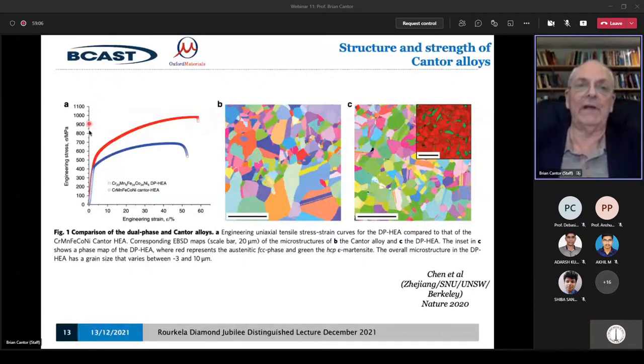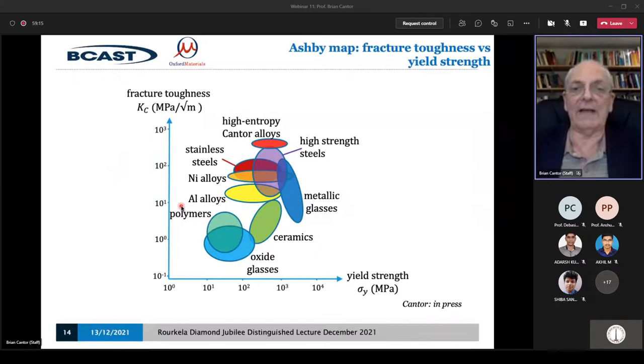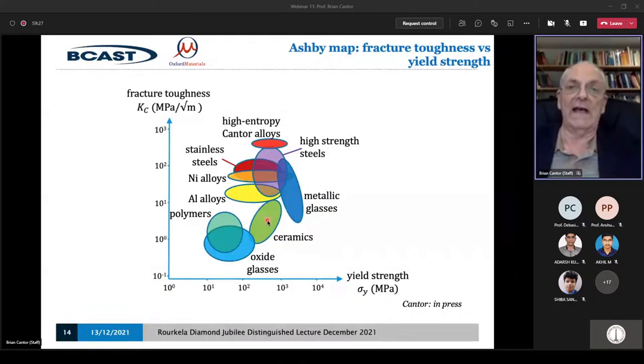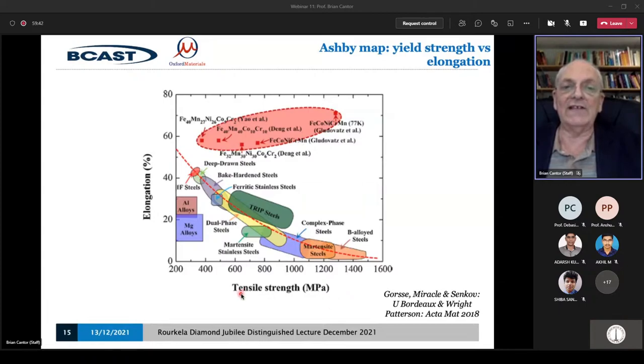Here's what's called an Ashby map, showing the fracture toughness, the resistance to fracture, as a function of the strength. And here are all different materials, glasses, metals, ceramics. And right at the top are the high entropy Cantor alloys. They have the best combination of resistance to fracture and strength, or formability and strength. If you home in on it towards that top end, you can see that here, and it's elongation now, or ductility, but that also goes with fracture toughness, resistance, and also with formability and strength. And you can see the Cantor alloys are all here, and these are the best high strength steels we've got, which we can use. They've got the best properties of any materials so far.